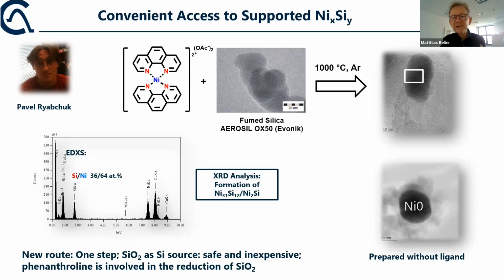The reason how these nickel silicides are formed is the presence of the nickel nanoparticles with organic reductants, which we used as a ligand, here phenanthroline, for example, at high pyrolysis temperature. High pyrolysis temperature means 1000 degrees. At this temperature, the nickel nanoparticles are formed by reduction of nickel(II) from the phenanthroline species. Phenanthroline acts as a reductant, and the surplus of the reductant in the presence of the nickel nanoparticles then reduces silica to silicide. So in fact, we are reducing silicon dioxide to metal silicides, of course at high temperature. But if you look more carefully into the known literature on the formation of nickel or metal silicides, typically much higher temperatures are needed to prepare this type of materials.